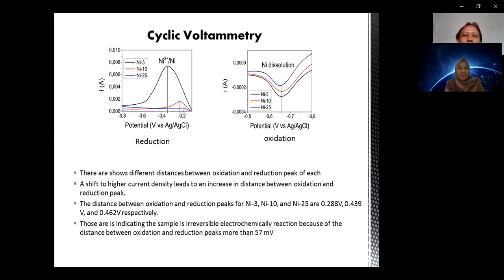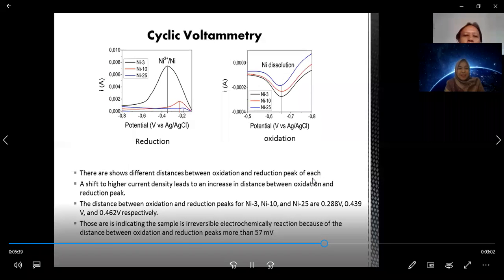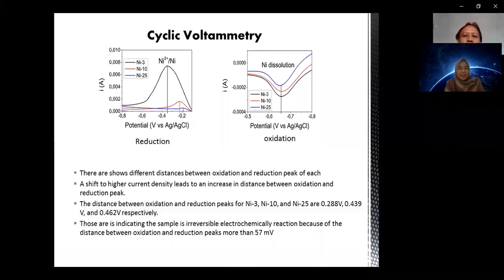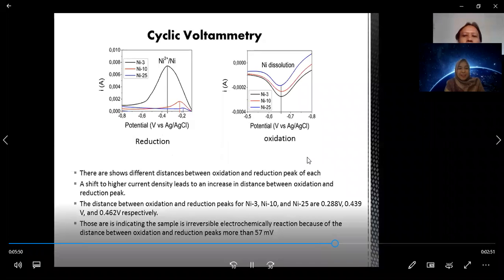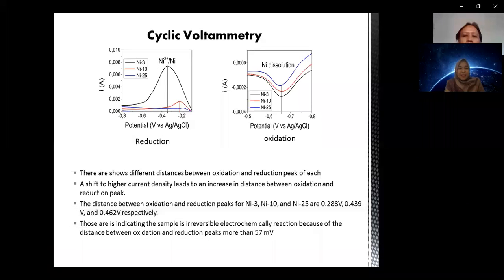We can see the cyclic voltammetry, reduction and oxidation. There is a varying distance between reduction and oxidation peaks in the 3 samples, indicating an irreversible electrochemical reaction because the distance between oxidation and reduction peaks is more than 57 millivolts.